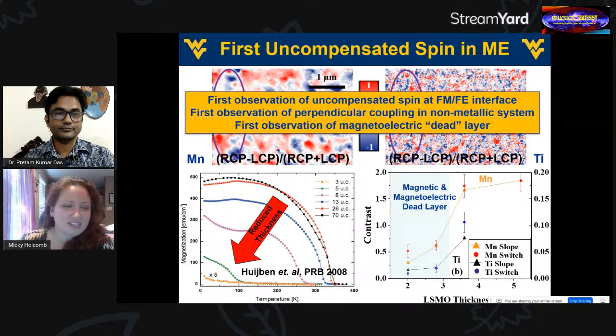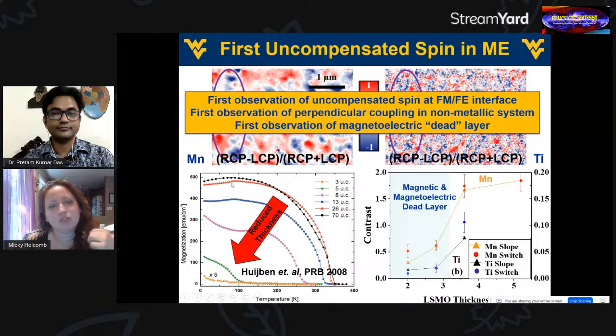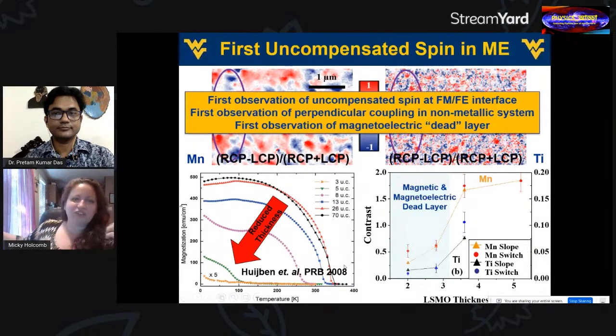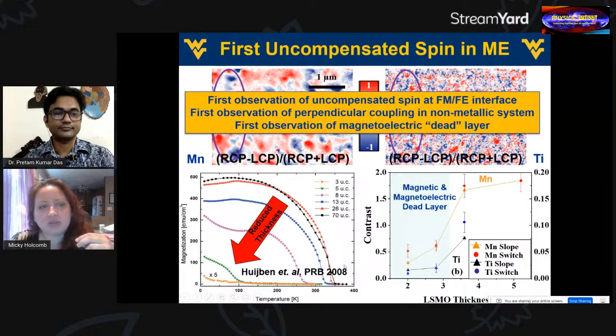All right, so here in this picture on the bottom, we show the magnetization versus temperature of a lot of different films of various thicknesses. And what you'll notice is between 70 unit cells to 26 unit cells, there's very little difference in the magnetization. In fact, I could show a whole range of samples from 26 to well above 70 where that magnetization doesn't change very much. So this is kind of a normalized magnetization, right? Normalized for volume. So up until 26 unit cells, our magnetization is pretty much what you would expect for the elements in the system. Maybe not perfect, but pretty close. As soon as you start going much below 26, though, you'll note that the magnetization drops off pretty dramatically.